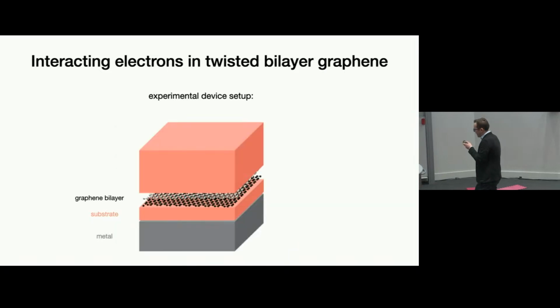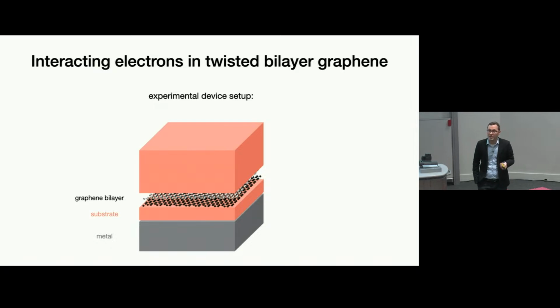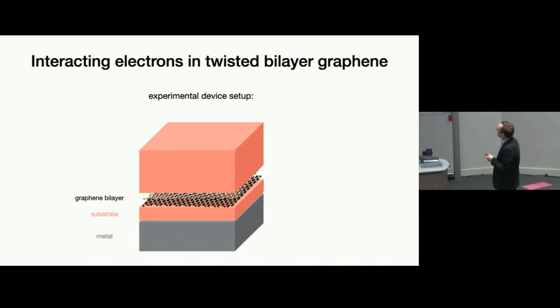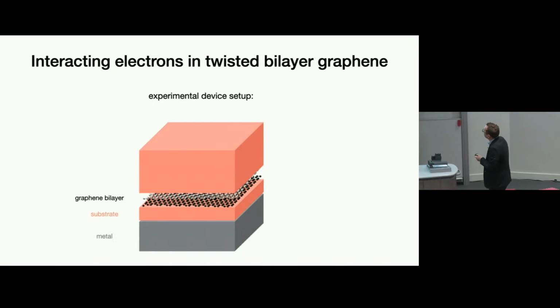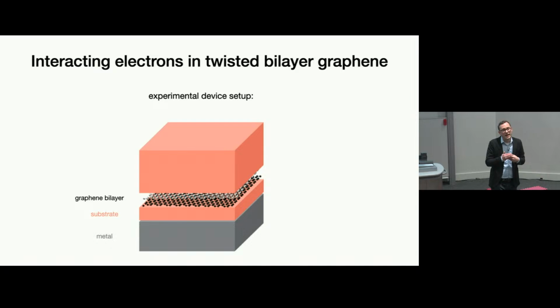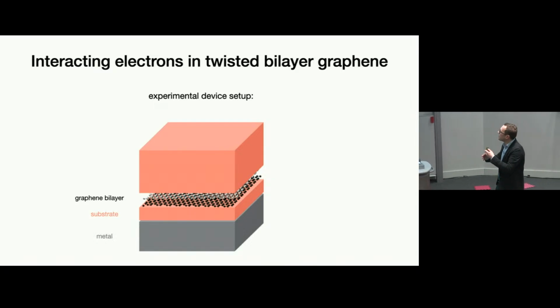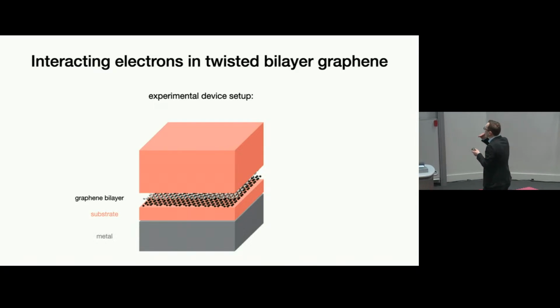So what had we forgotten? Well, when you look at a real device that is used in experiments, you have your twisted bilayer graphene, which is what we had been studying. But actually, in a real experimental device, the graphene sits on an insulating substrate, and underneath that substrate is a metal, and that metal is connected to the graphene so that we can measure the flow of electrons through the graphene. And we hadn't included the effect of that metal. So what does that metal do?